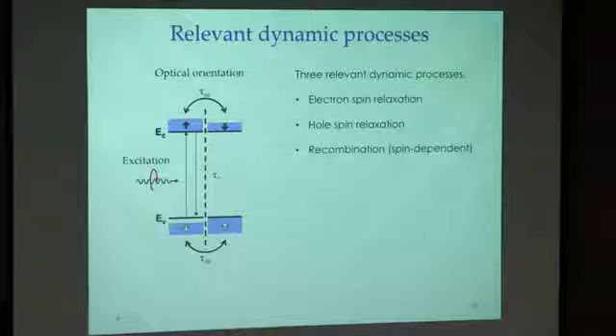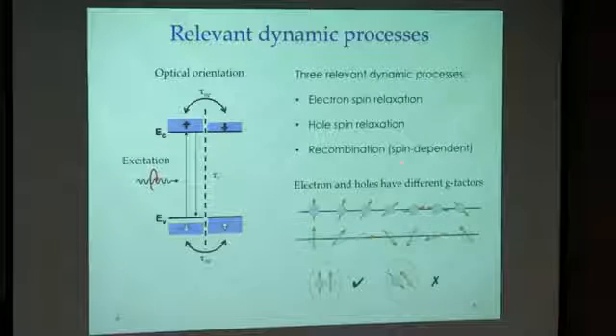The recombination is also spin dependent. Like in our measurement, we have determined that the recombination time is very long. So what's relevant are only those two, or to be precise, it's spin polarized exciton states relaxation. Okay. Here, what I mean by spin dependent recombination is the following. Say, electrons and holes have different G factors. They precess at different speeds.